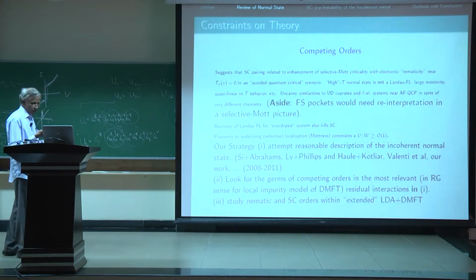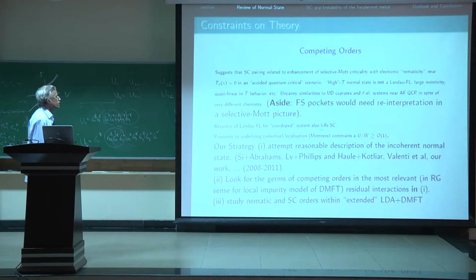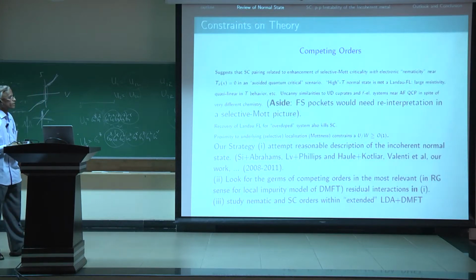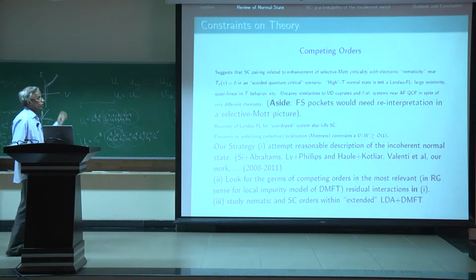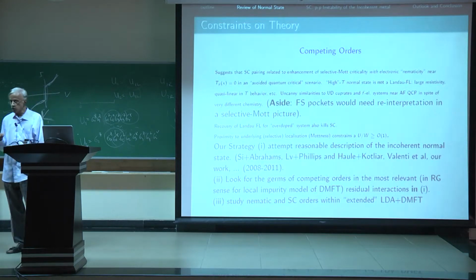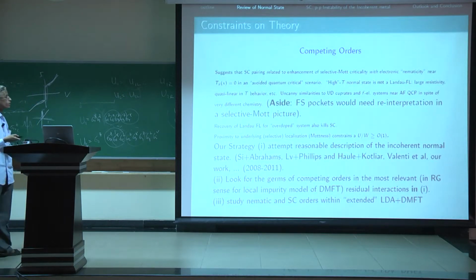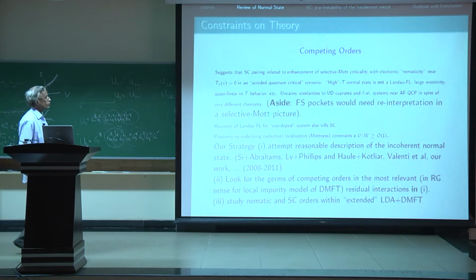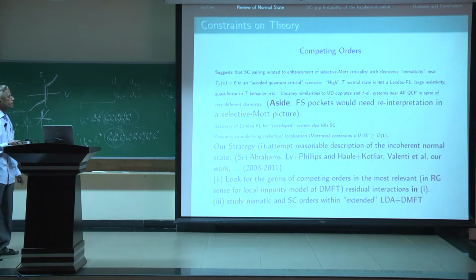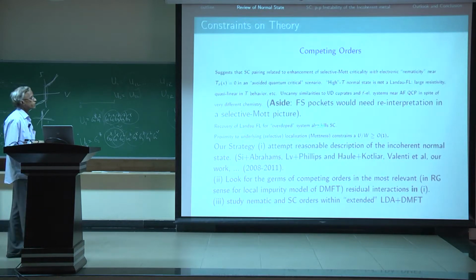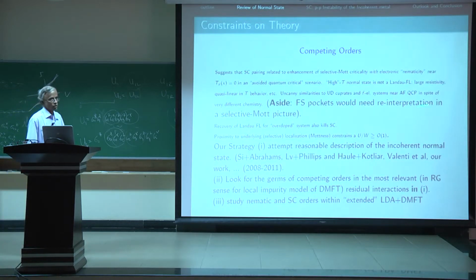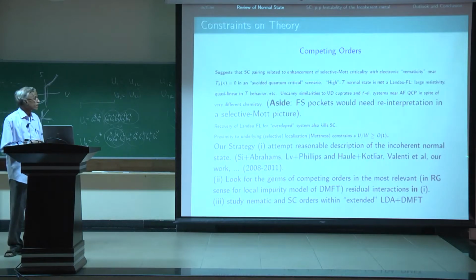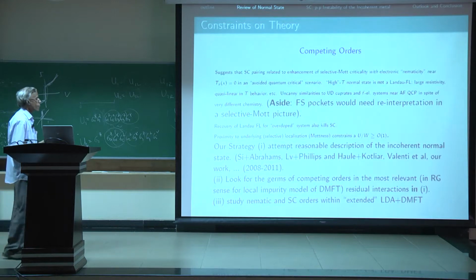Okay. Right. So on the other hand, one also knows from all these examples that basically if you overdope, you gradually go over to a more or less conventional looking metal, at least at very low temperatures. But the important thing to notice here is that whenever you recover conventional metallicity, you also destroy superconductivity. So there is a direct correlation between having a bad metal and unconventional high Tc.